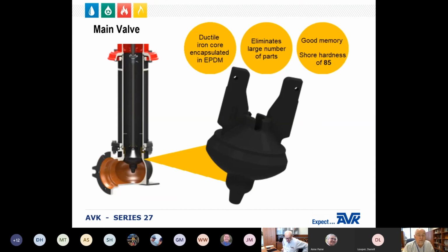Located at the bottom of the hydrant is one of the most important features of the hydrant. It's the one-piece main valve that was patented by AVK. The main valve has a ductile iron core that is encapsulated with EPDM synthetic rubber. EPDM is resistant to chlorine, chloramine, and UV light to provide a long service life. The AVK main valve eliminates the large number of parts used by our competitors in their main valve, thus reducing your spare parts inventory, and it also makes it very easy to replace.